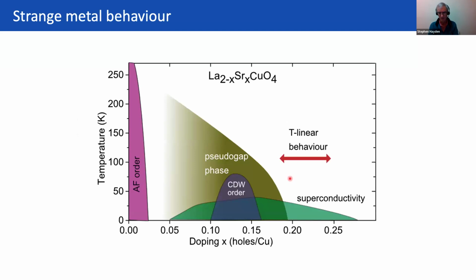So a little bit about strange metal behavior. This is seen most clearly in the overdoped region of the superconducting phase diagram. So here we've got LSCO, and what do we mean by the strange metal behavior? Well, of course, linear T resistivity is known for a long time in cuprates, and that's the primary thing. I guess in recent years it's been shown that it continues down to very low temperature, and you can see when you remove the superconductivity with a magnetic field that it's still linear behavior. And the other aspect to it, which I'm not going to show much data about, is the specific heat. In general, people taking things beyond the cuprates, when people talk about strange metal behavior, they often also have unusual behavior in specific heat with T log T terms, for example, upturns at low temperature and particularly large specific heats.